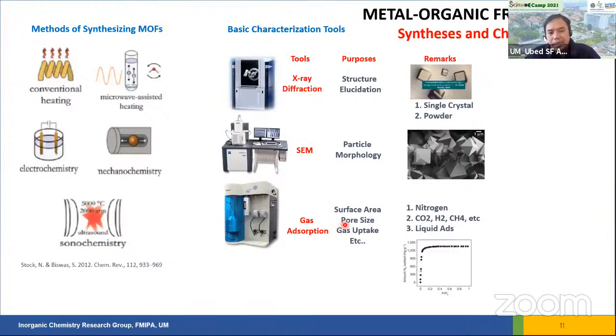We can determine the surface area of the MOF by using nitrogen or carbon dioxide as the gas source. Another one using gas absorption is hydrogen or methane. We can examine how much hydrogen or methane is absorbed into our MOF. So we can use a gas absorption machine like this one to determine the surface area, pore size, and also gas uptake.